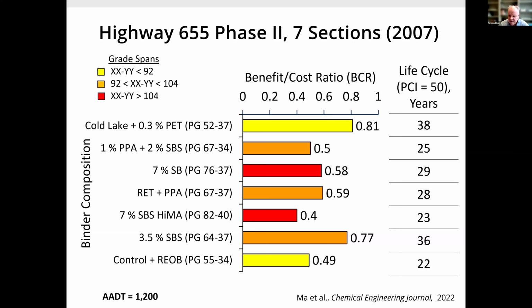Today, it's marketed to death, highly modified binder. There may be benefits in moderate coastal climates with very heavy traffic, maybe New York City, maybe Miami, maybe in China, in Shanghai. In China, they put in 10, 12% SBS polymer. I would not advise it in Ontario. I would advise against it. This slide also shows if you just put REOB, this motor oil residue, in a regular good asphalt, you lose 40% of the benefit cost ratio. And that's a lot. For municipal budgets, where you squeeze every dollar, this is a massive amount.